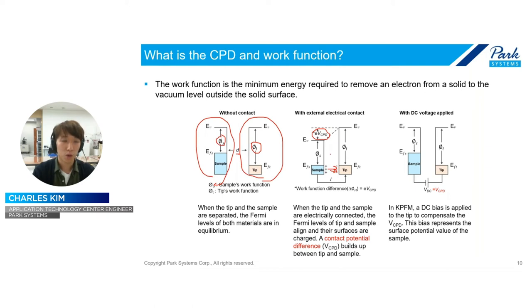So this energy gap difference makes an electric field between them, like this. But our purpose in KPFM is to eliminate, to compensate this field. So if I apply a DC bias between the sample and the tip, equal to the VCPD, then I can compensate the CPD value. So from this kind of circuit, we can know the potential value of the sample surface.